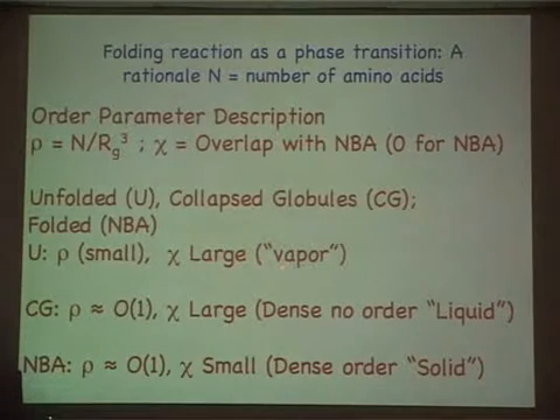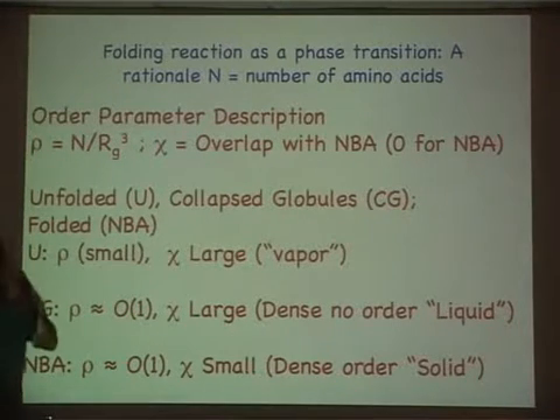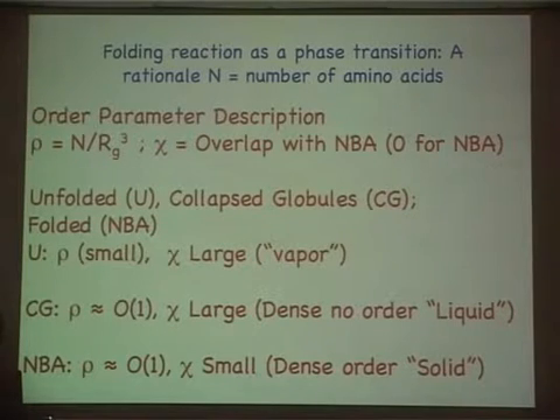And a small chi means it is exactly the same as the native state or the folded structure. If you want, you can think of the unfolded state as a vapor, a low density fluctuating object, kind of like a vapor, if you wish. This is a globule, a collapsed globule. The rho is expected to be of the order 1 because RG in fact scales as n to the 1/3. So rho is of the order 1, but chi is still large because this is a compact object that's fluctuating, still not exactly the same as the native state. That's a second phase that you can think about, and if you want, you can assign that to be a liquid.